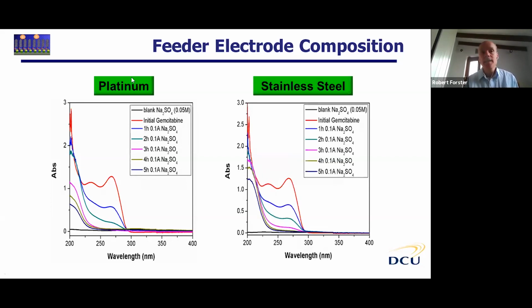We can change the nature of the feeder electrodes. We started using platinum, then went to stainless steel. You do see some slowing down of the overall reaction - it takes about another hour using stainless steel as the feeder electrodes. The reason for that is the electric field distribution is a little different with the stainless steel mesh than with the platinum.